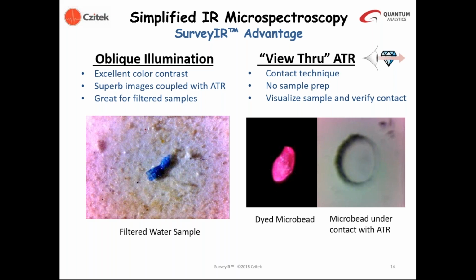in that we can illuminate samples with oblique illumination, which is also called dark field sometimes. But for scattering samples like this microplastic, which is on the surface of a filter paper, in this case, this was a filtered water sample, and we see this little microplastic, you see excellent color contrast and superb resolution in these images. And this is probably almost the universal illumination mode that we utilize for microplastics, and it's very good for scattering samples.